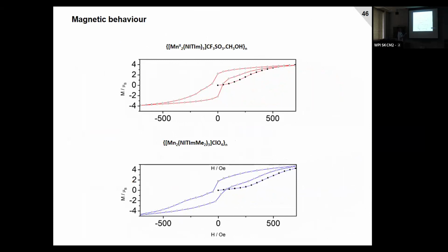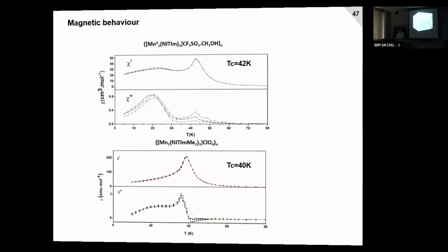And if we look at the magnetization versus magnetic field, this is the first magnetization. You can see that the first magnetization shows some points, so this is reminiscent of metal-nitroxide. And then the hysteresis loop does not superpose with the first magnetization, which is due to the fact that we have metamagnetism. Metamagnetism is a field-induced transition. It's induced by the magnetic field.